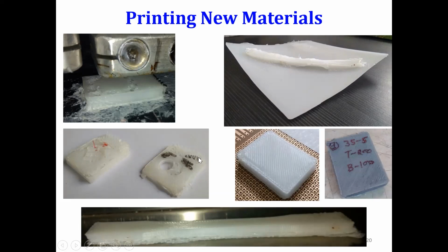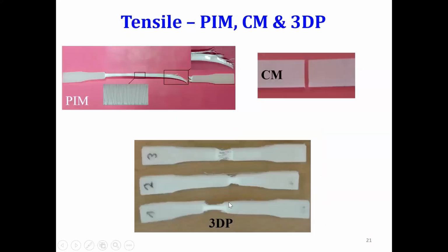There are some defects here, and after tuning the parameters, as I said, printing temperature, chamber temperature, and bed temperature, along with the nozzle temperature, we could get a good sample. And this is where a good amount of time, though we follow an engineered way, needs to be invested to get a proper sample in new materials development. And then this is the sample of a composite blend wherein fly ash cenospheres were infused. And finally, we were able to print an ASTM D638, 165 millimeter length dog bone sample completely.